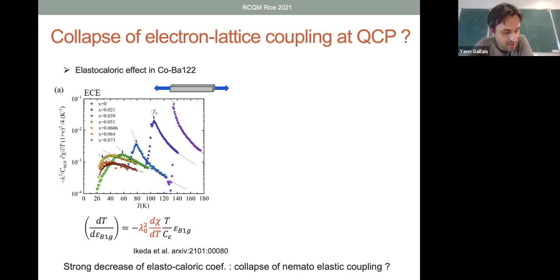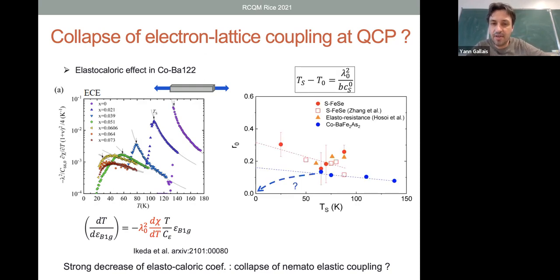Just recently, regarding this nematic coupling, there is this elastocaloric effect coming from the group of Ian Fisher, where they saw a huge decrease of the elastocaloric effect in cobalt barium 122. This collapse was attributed to a collapse of the nemato-elastic coupling upon approaching the critical doping. So if I look here at my plot of R_0, the blue points are now the data coming from our data in cobalt barium 122. What I was doing before was an extrapolation down to the critical point. So is it possible that in fact this coupling goes to zero at the critical point?